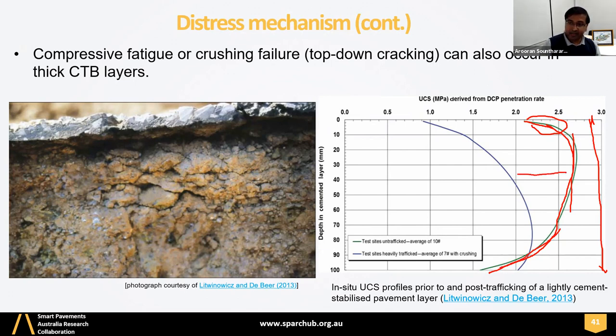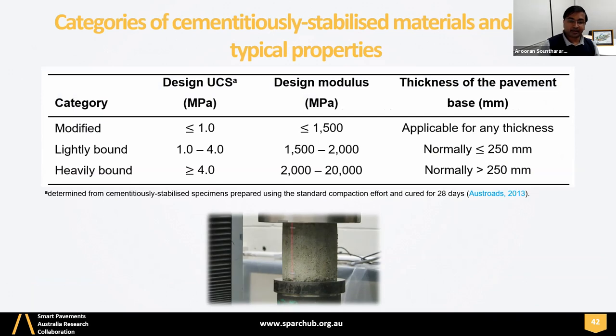Then after trafficking, what happened? This trafficking had a certain number of cycles. I can't remember the exact value, but it is more than 10,000 cycles. Your UCS has gone down from the initial value, in particular closer to the top part of the pavement. So what does it mean? This pavement has progressively failed in compression, not in shear. This is a compression failure because you have reasonable cement in this pavement. So UCS has gone down, which indicates the crushing. There's a UCS failure. This was taken during my PhD, when I was testing a cementitious material. This is a typical UCS, unconfined compressive strength, failure.